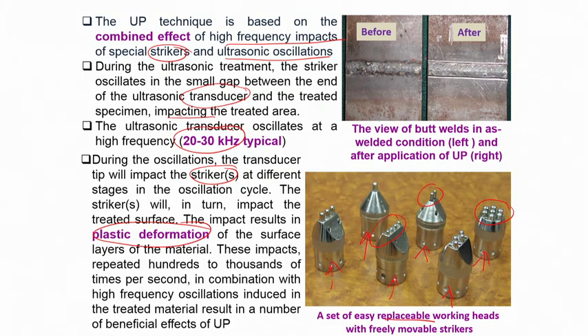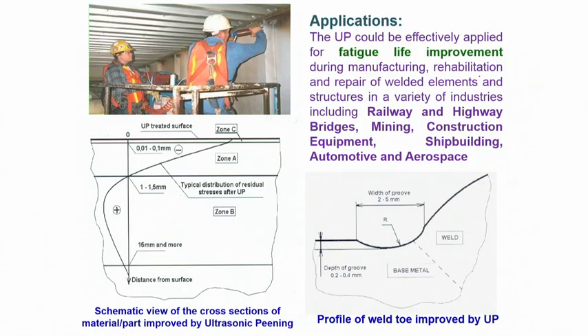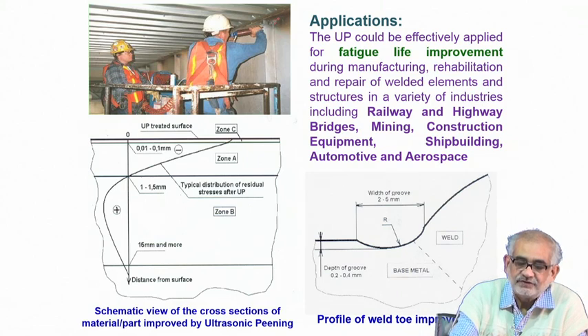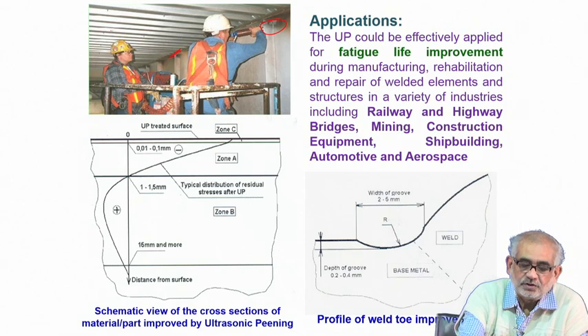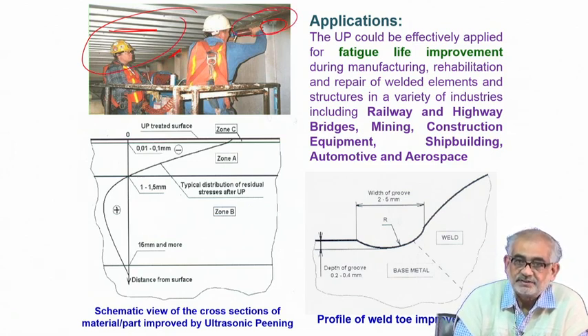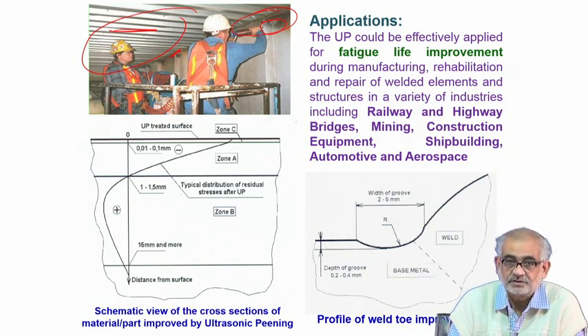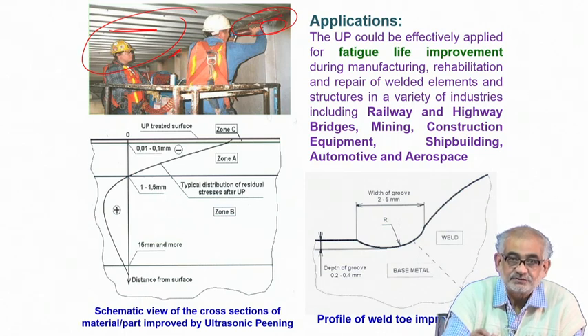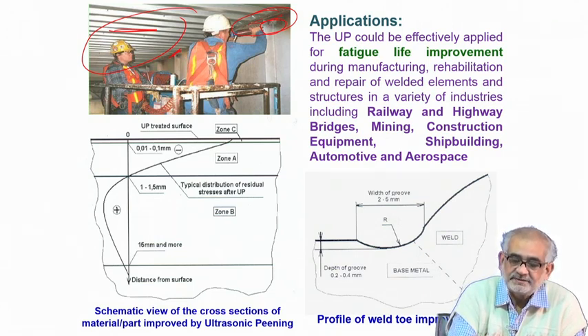A welded joint in the as-welded condition — after such ultrasonic peening — will appear very uniform, and if you measure the residual stress by X-ray diffraction you will find that the state of stress is negative or compressive in nature. The advantage is that in construction activities where you have to weld a corner or treat certain portions on the rooftop, you cannot dismantle the whole roof or the joint and take it to a machine. In order to extend the life of such welded joints at difficult-to-access corners or large surface areas, all you need to do is take the ultrasonic peening gun and treat the surface to create this state of stress.